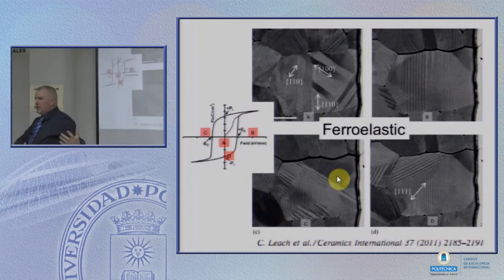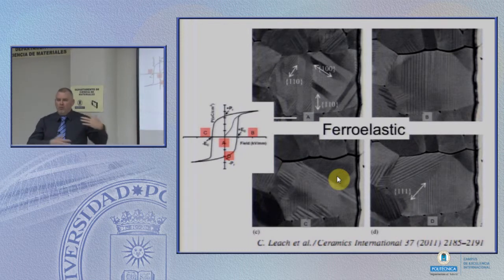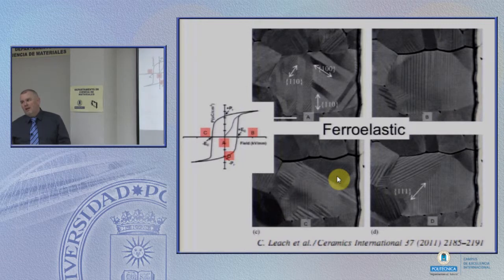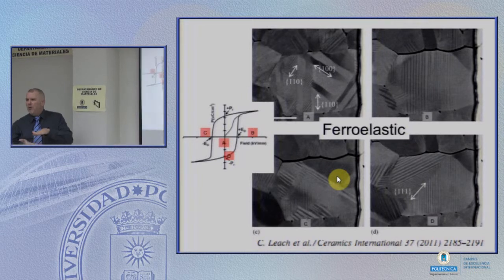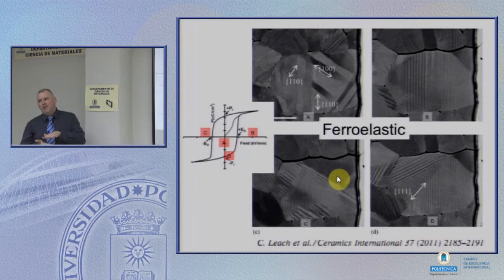If you take one of those materials out of the furnace, you process it. If you buy one that's just been processed in that way, it's dead. It doesn't do anything. It's not an active piezoelectric material. You have to pole it. To pole it, what we usually do is apply a high electric field to it, usually at an elevated temperature in order to get the domain walls to move a little bit easier. And then we freeze it into that structure so that it is now an active piezoelectric.